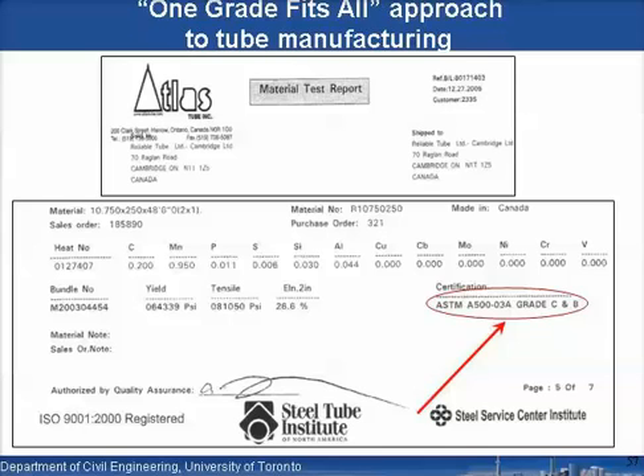Now it's odd that of course we'd have the same overstrength factors for various types of materials and different grades, because if we look at modern production methods and a typical material test certificate that we see now, tube companies are largely making on a one grade fits all sort of basis, because they don't want to have lots of different coils for different grades, for ASTM A500 grade B and grade C, so they would buy one coil to suit them both. So we get what's called dual certification at the moment. So those RY factors were actually based upon a study assuming that the product was grade B, but actually it's usually always made to also be grade C. So those RY factors are in fact very conservative.